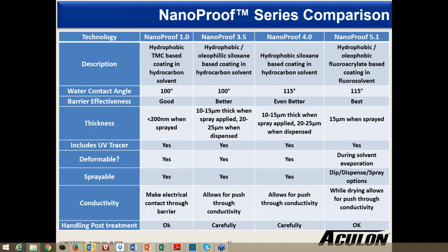NanoProof 1.0 is probably the outlier in terms of thickness. That goes down in very thin coatings, and it's really meant for customers who just want hydrophobicity, just to prevent water ingress through small ports, or if water does get on the board, it slides off, that kind of thing. 3.5 and 4.0 are beefed up in terms of barrier properties, ion migration, that kind of thing. So they tend to be a good bit thicker, 10 to 15 microns or so.